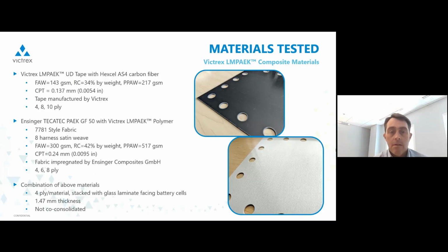The materials we tested all are based on Victrex's LMPAEK polymer. There were a few different material combinations that we went with. The first being a unidirectional tape. We used Hexcel's AS4 UD carbon fiber for that. It's a 143 GSM, 34% resin content, unidirectional, so a pretty standard aerospace material type. It's just over 1/8 of a millimeter thick per ply. We make the tape in the UK, and the laminates that we tested here were 4, 8, and 10 plies thick.